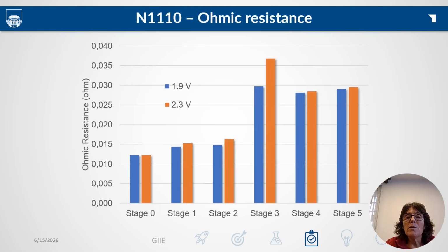We plot the ohmic resistance as a function of stage. We see a small increase during stages 1 and 2, a sharp jump after stage 3. The ohmic resistance remains elevated throughout stages 4 and 5. This is our first signature of irreversible degradation.